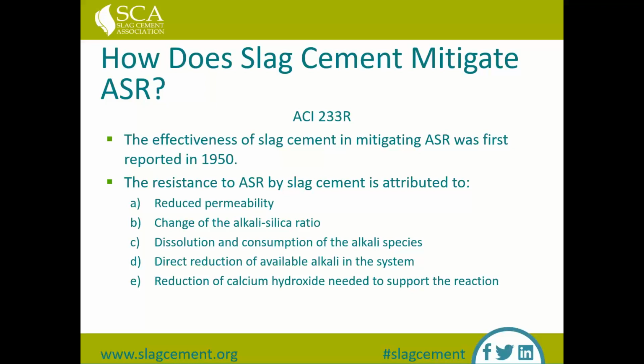The next 3 factors listed there have to do with alkali contents, both in the direct reduction of available alkalis in a concrete system, as well as a reduction in the alkali silica ratio in the concrete, and also the actual hydration of the slag itself consumes some of the alkalis. So when you've got slag in your system, it helps reduce the available alkalis that might contribute to ASR damage.